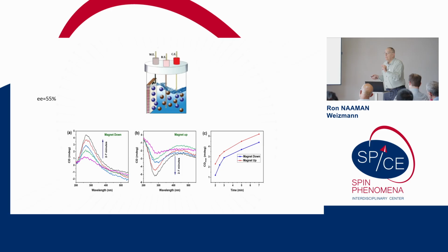So we do the polymerization with spin-polarized electrons. And what we find, here is the CD spectrum, is that for spin pointing in one direction, the polymer shows CD that's going up. In the other case, it's going down. So we make the opposite enantiomer by flipping the spin.